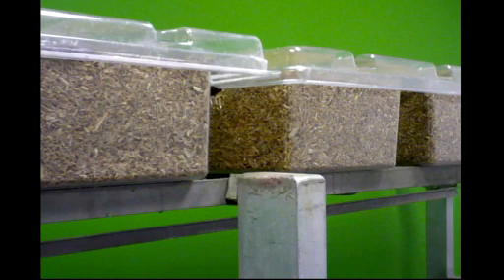So this is a time-lapse video. I'll press go in just a minute, but let me explain what's going on here. In our factory, we've sourced agricultural byproducts. These corn stalks are providing an additional revenue stream to local farmers. We've steam cleaned it and then added just a tiny amount of mycelium. It's microscopic. There's less than 1% in this mix.